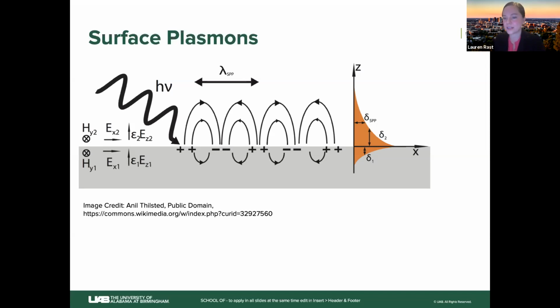All of these interesting quasi particle interactions allow for a really wide variety of behaviors that are interesting in different areas of optoelectronics. Okay, so for example, the strong optical confinement of plasmons relative to the wavelength of light leads to really intense enhancement of the electromagnetic field locally. The field enhancement in metallic nanoclusters can actually provide a 10^15 intrinsic enhancement factor of the field, allowing for things like single molecule detection via surface enhanced Raman spectroscopy. So we're talking about really high resolution imaging as one of our important applications for these types of materials.